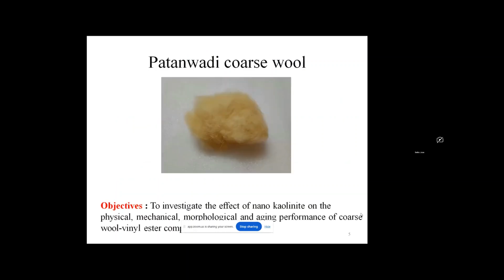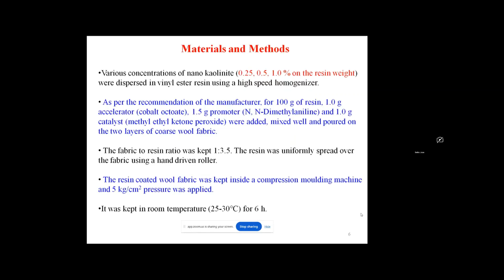So I have taken Patanwadi coarse wool, which has a typical fineness of more than 40 microns, and I made some composites using vinyl ester. Then I added nano kaolinite as a filler to enhance the mechanical properties of the composites. So these are the materials and method.